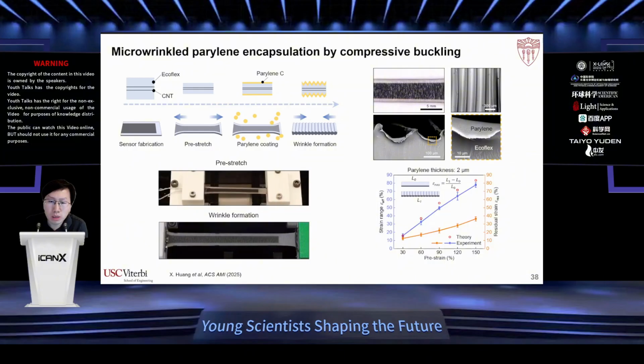And you can see here, because the parylene coating process is vapor-based, the parylene layer can actually diffuse into the silicone layer underneath, forming a very stable and strong adhesion interface.